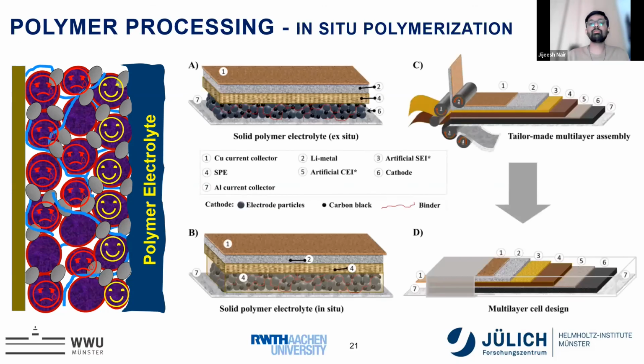So it is important when we think about solid polymer electrolyte to go for in situ based systems, where you deposit the polymer electrolyte also in the bulk of the electrode, and use more solvent-free techniques or other kinds of fast processing to improve the battery performance. And besides, it is also important to look at the interfaces, like the solid electrolyte interface at the lithium metal surface or the cathode electrolyte interface at the cathode surface. So even when you use thinner fabrications and in situ processing, you can fine tune these interfaces and get a system which is a multi-layer system.